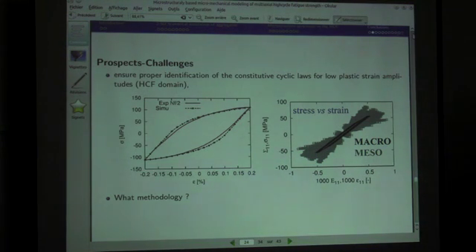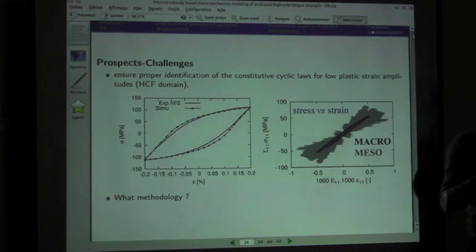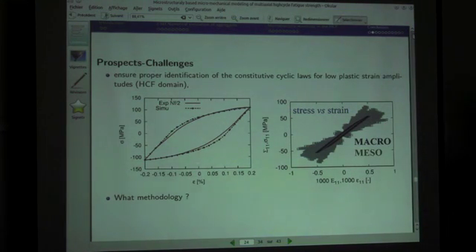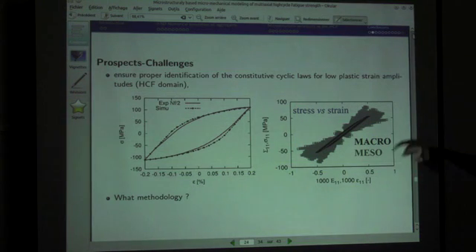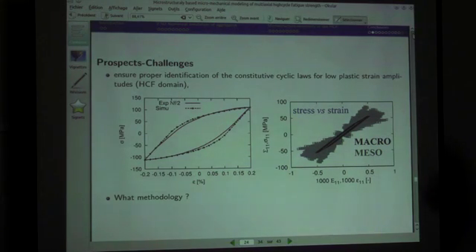The first problem we have is how to identify the cyclic behavior. We can do it for large plastic strain. So here we have large plastic amplitude. You can do a macroscopic test and identify the parameters for the crystal plasticity modeling. However, when we go to very high cycle fatigue, we go to very, very low strain amplitudes. And the validity of the laws that we are identifying at the micro scale for large strain amplitudes, it's not really sure that it's going to work for low strain amplitudes.